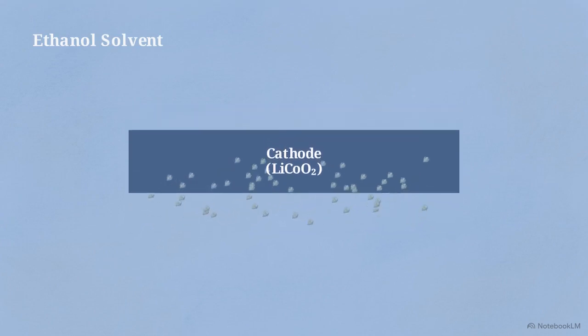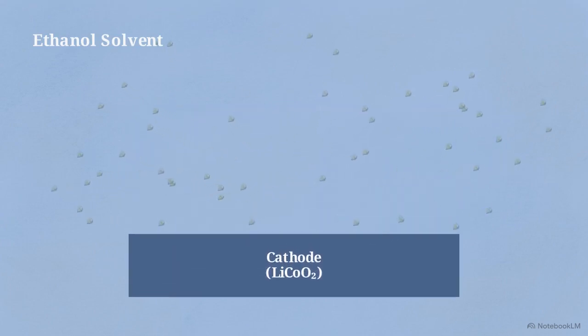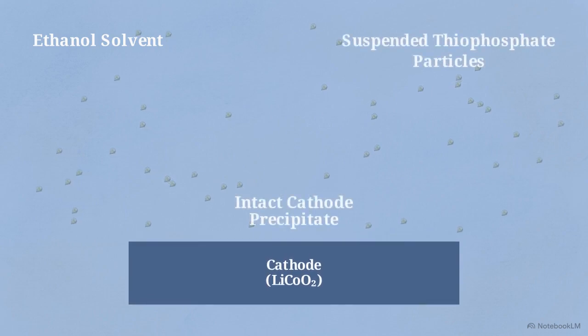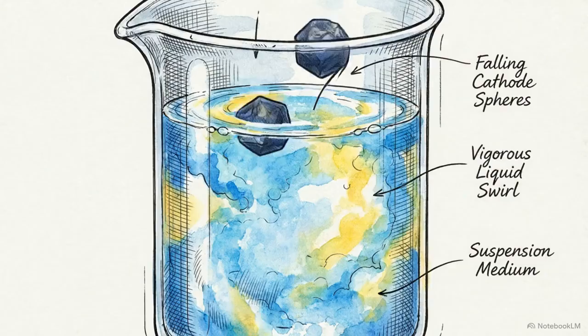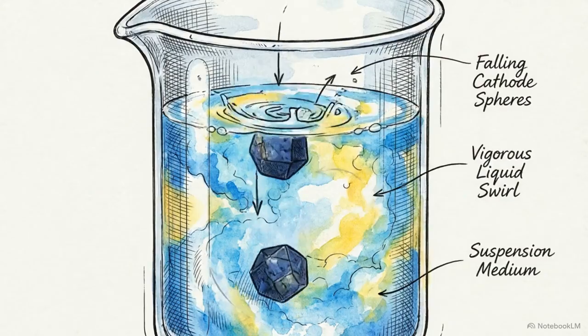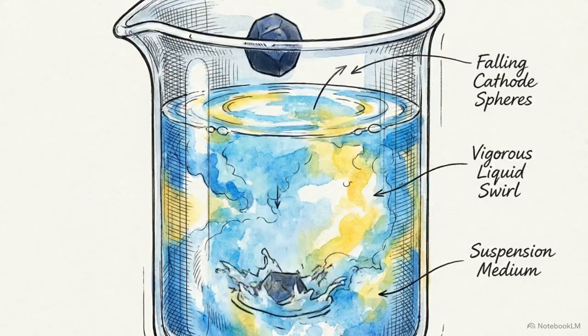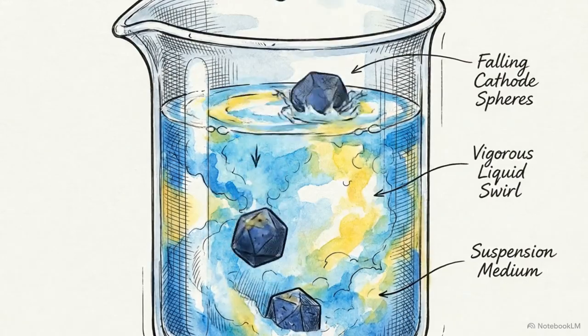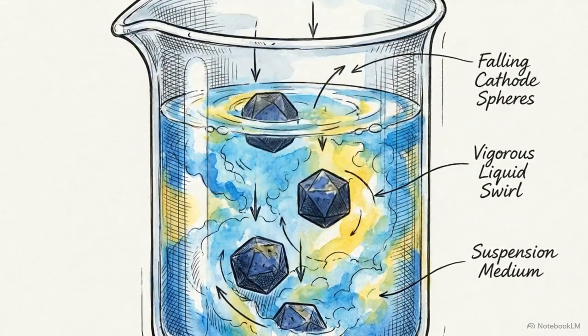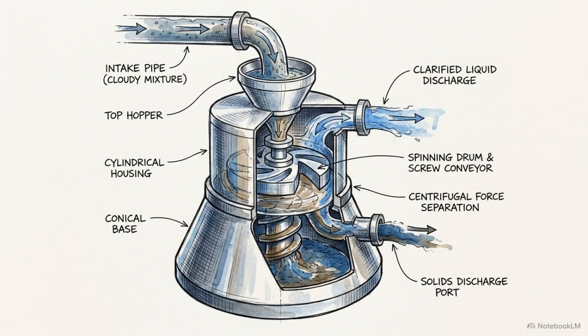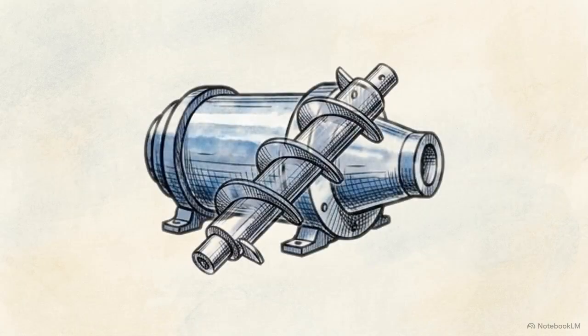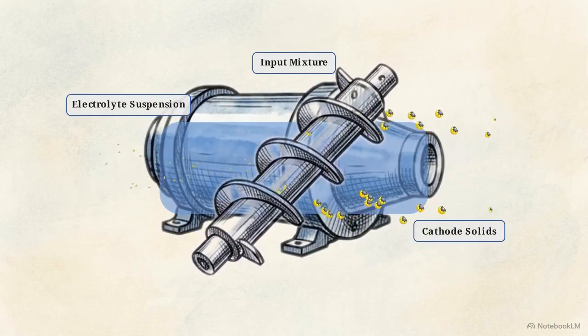The ethanol interacts with the thiophosphate units inside the sulfide-based solid electrolyte, causing the solid layer to dissolve cleanly into a liquid suspension. Crucially, while the solid electrolyte dissolves into ethanol, the spent lithium cobalt oxide cathode does not react. It remains completely solid. Now that the cell is split between a liquid suspension and solid particles, the mixture is fed into a centrifugal decanter. The spinning forces cleanly separate the heavier solid cathode precipitates from the dissolved electrolyte.